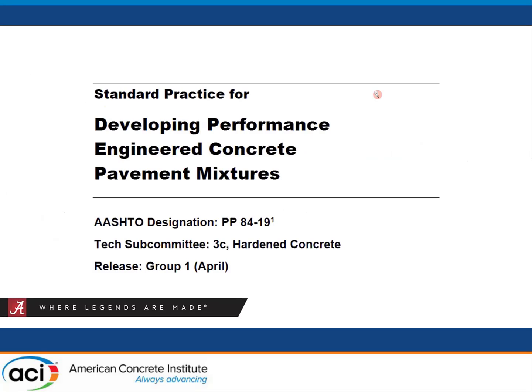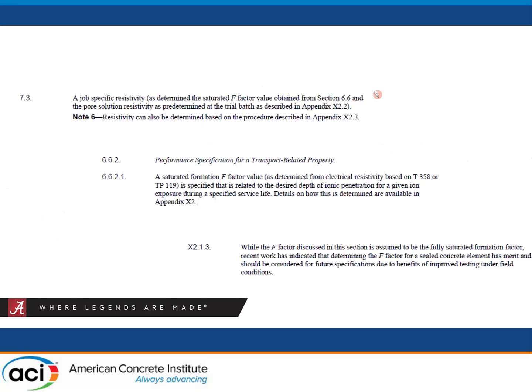And when we start thinking about performance engineered mixtures and looking at PP84, and we're specifically looking at resistivity measurements, we have some guidance on how to do these measurements and what we're looking for. And it mentions a saturated formation factor value. When we look a little further, most of the PP84 documentation is assuming fully saturated. However, recent work, not mine, others, has suggested that maybe a sealed formation factor has some merit, and maybe we should consider this for future specifications.